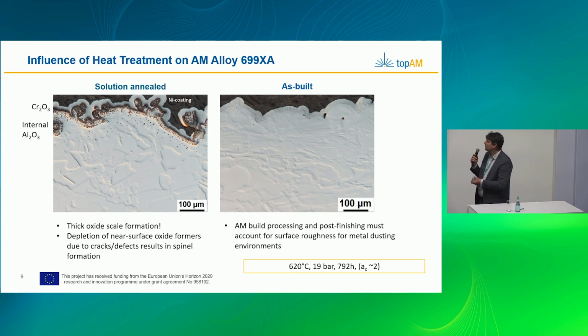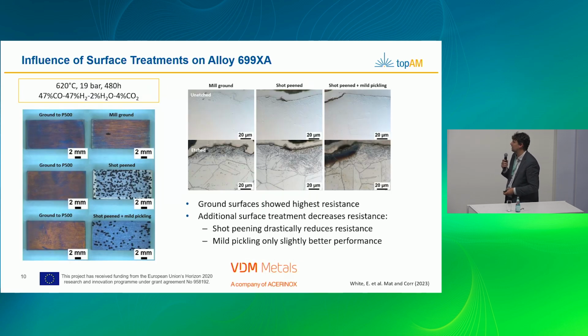Now the problem is here with the solution annealing, there's some aluminum in those alloys, and especially aluminum oxidizes at very, very low oxygen partial pressures. So during the solution annealing, you can see here that some aluminum close to the surface was internally oxidized already. And of course, this is weakening the later corrosion behavior. So this is something that you should keep in mind, and this is another reason why a final surface treatment is necessary.